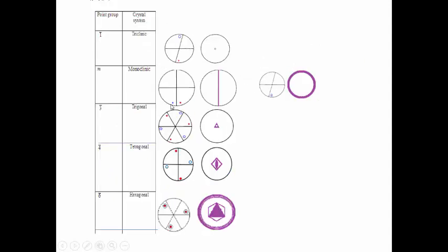And here we put them all together. We've done them all. The only thing that's a little different here is these 2 different orientations of the mirror plane. We could orient it along, say, the y-axis here, and we have the plus going to the change of handedness across here. On the other hand, if we put the mirror plane in the plane of the board, the plane of the computer, we create this bullseye effect, and that's what our symbol looks like. These are exactly the same monoclinic system. It's just down 2 different axes.